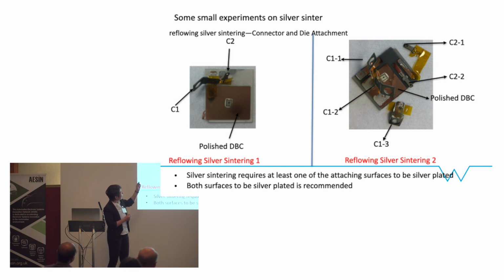Finally, we found that in both situations our die can be attached on the DBC board, but the connector will always fall off directly after you take it out of the oven. So we can conclude here that silver sintering requires at least one of the touching surfaces to be silver plated, and both surfaces being silver plated is recommended. So finally, after this experiment, we decided we will keep the silver sintering for the die attachment, which is the most important part, but for the connector attach, we'll keep to solder material.